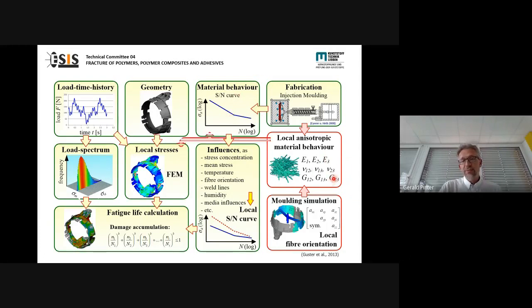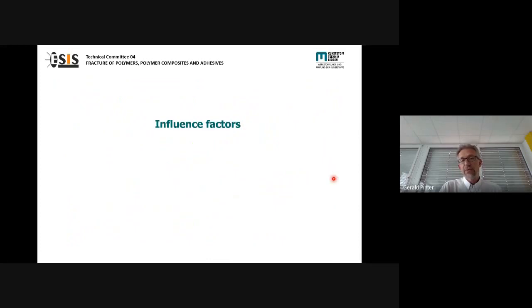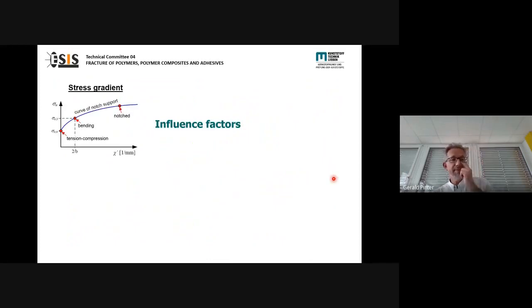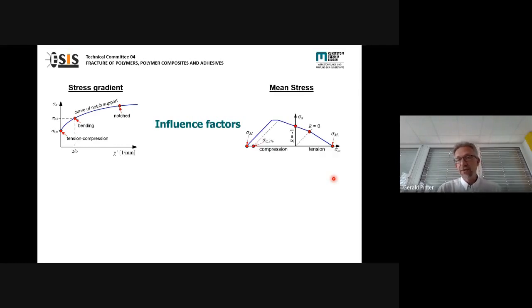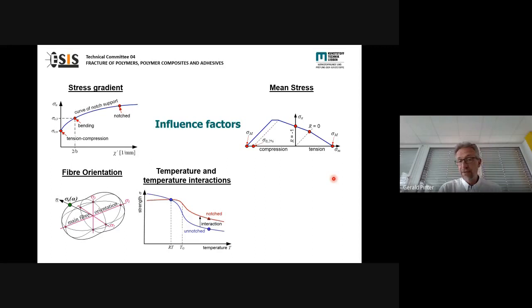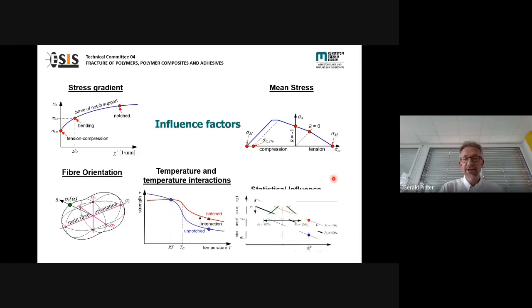The input parameters that we have implemented over the last years are different affecting parameters like the stress gradient. So if you also have notches in your components, of course, the influence of the mean stress, of the R ratio, the fiber orientations as explained, the temperature effects in the polymers. You do the tests, the Wöhler lines at different temperatures, and of course, statistical influences.